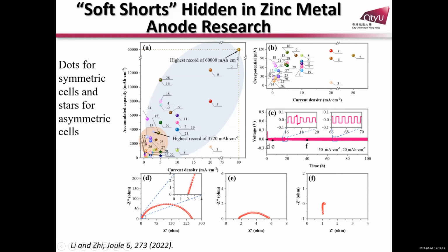You see that the accumulated capacity for the symmetrical batteries is getting very large. But if you compare with the full batteries, it's much smaller. And if you compare the reported overpotential, you will also see quite diversified overpotentials. It can be 80 or it can be very small. So we know that there might be some problems. We call it soft shorts.